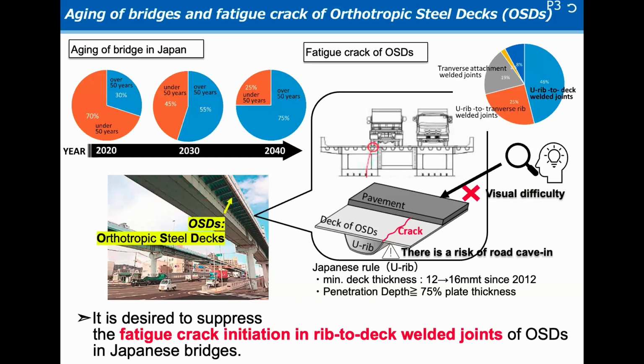When the fatigue damage of OSDs is examined in terms of place, rib-to-deck welded joints are the most common. This fatigue damage is caused by cyclic rolling by vehicles passing over the road surface. These fatigue cracks are difficult to visually inspect unless we peel off the pavement, and there is a risk of road caving. So it's desired to suppress the fatigue crack initiation in rib-to-deck welded joints of OSDs in Japanese bridges.